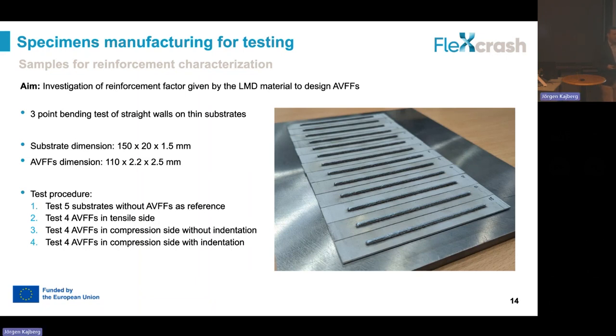Of course, usually to characterize material, we do tensile or fatigue testing on bigger components. This could be, however, a problem when we try to characterize our AVFFs. This is because with 3D printing, if I'm trying to print a relatively small but long wall, or a big block of material out of which I can mill out my samples, I will end up with completely different microstructures, because the material is subject to completely different cooling rates if I build a very small sample or a very bulky one. Therefore, in this case, we cannot deposit samples following standards for material testing, but we have more or less to create our own testing strategy to characterize the material and have the material properties that will be used in the simulation to get the final shapes that we want.